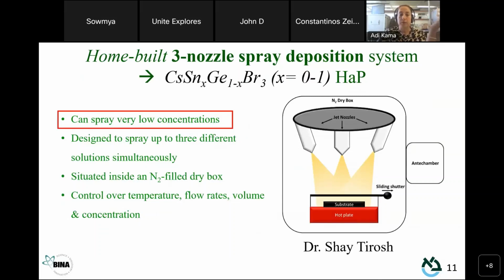So due to the low solubility of those materials, we decided that we need to work with them, and we just need to find a different deposition method that can work with low concentration solutions. And that's where we decided to go for a 3-nozzle spray deposition that was built especially for this purpose, together with Dr. Shay Tirosh from my lab. The main idea is that we can spray low concentration solutions. The spray is located inside a dry box filled with nitrogen, so the environment of the deposition is without oxygen and humidity. And we have control over the temperature, the flow rate, the volume, and the concentration of the deposition.